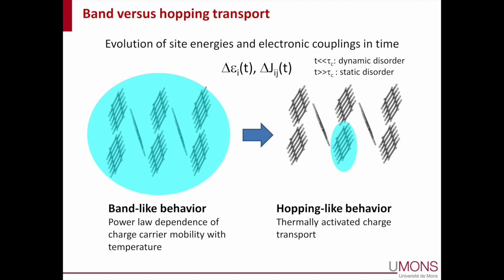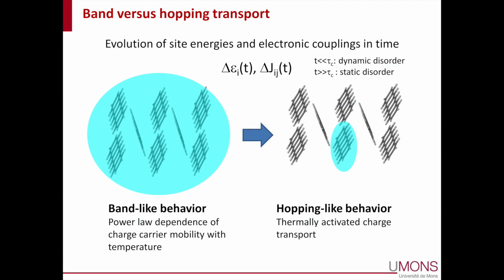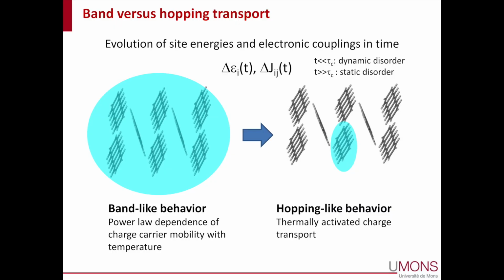But what happens in reality is that those molecules are not fixed in space. They fluctuate in their relative position with respect to the equilibrium geometries, and that gives rise to changes in both the site energies, the energy of a charge sitting on a molecule, which will fluctuate in time, and in the quantum mechanical coupling between neighboring molecules. And that drives self-localization onto one molecule in the case of a system where transport is driven by hopping and is thermally activated.